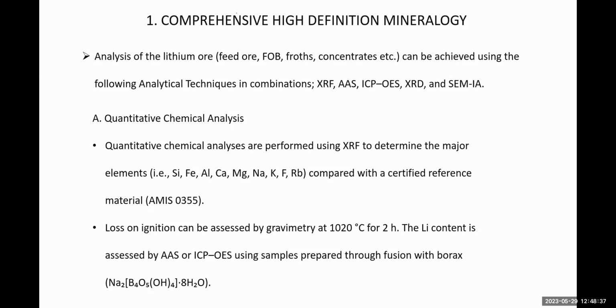Loss on ignition can also be checked by gravimetry at 105. Sorry, that is not 1020. It's 105 degrees centigrade for 2 hours. These are also parameters we check on the lithium mineral.